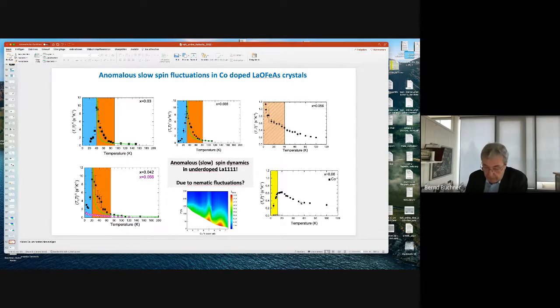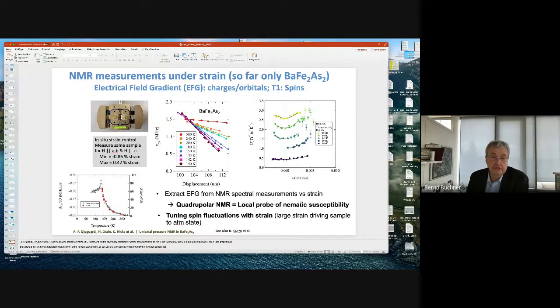Can we shed more light on that? And this, I will just mention that, of course, what you can do now is strain-dependent measurements of the NMR. You can really try to understand this coupling in more detail. We and also other people did that on BaFe2As2, where the crystals are large enough. And indeed, what you can do here, you can really follow, on the one hand, this electric field gradient, this orbital order as a function of strain, so you can induce this nematic instability, and then you can even induce magnetism, and that's just shown here.